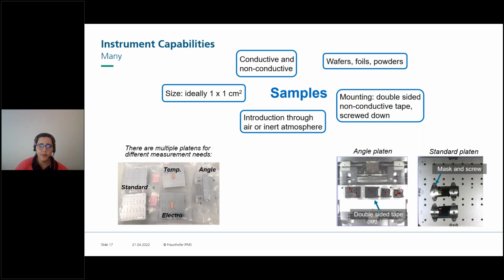We have multiple sample holders for different measurement needs. So you have a standard platen, which is just a flat surface where you can mount your samples either by using tape or mask and screw, and you can normally measure with a takeoff angle of 45 degrees. We also can, since we can do temperature measurements, we also have a special holder for this. We can also do electronic measurements. And we have a special platen for angular measurements, which we can go from 5 to 90 degrees and as many steps as you require.